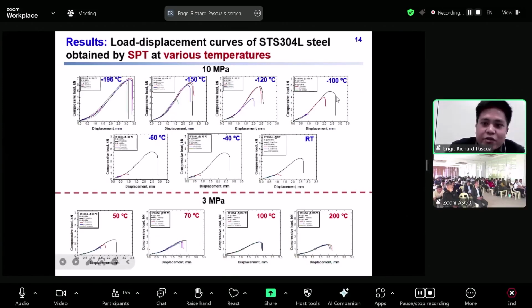But when we decrease the temperature from negative 100 to negative 150 degrees Celsius, the punch velocity effect was noticeable, in which the highest punch velocity showed the highest value compared to the lowest punch velocity. Therefore, there's an improvement of hydrogen embrittlement resistance at this temperature condition, particularly at highest punch velocity. And when we lower the temperature to negative 196 degrees Celsius, the load displacement curve obtained under hydrogen environment corresponds to the nitrogen environment in all punch velocity, which is showing that there's no significant hydrogen embrittlement effect at this